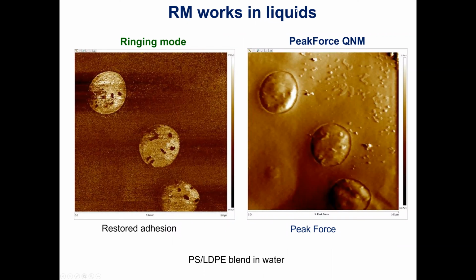Ringing mode can work in liquids. Essentially, we need just only a few oscillations, like 1 or 2, maybe 1.5. 2 oscillations after disconnection will be sufficient to extrapolate signal and get this information. This is, for example, restored adhesion on, again, low-density polyethylene, polystyrene in water. This is actually pretty destructive imaging, so that's why you can see erosion starting in low-density polyethylene in water. And this is just a regular height image for comparison.